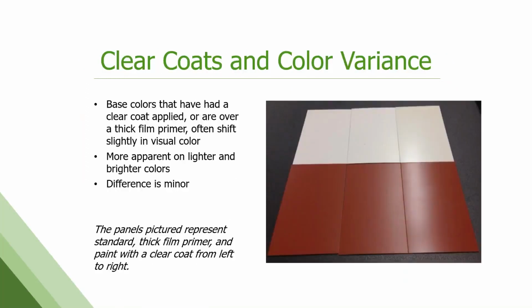Word of caution on clears, not too big of a deal, but you will get a slight shift in the visual color with and without a clear. It tends to yellow it just a tad. This will be more visible on a lighter color than a darker color. But, you know, if you find yourself working on a job where that needs a clear coat, make sure you ask for color samples with the clear coat so you know exactly what it's going to look like.